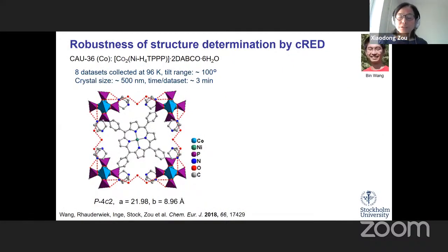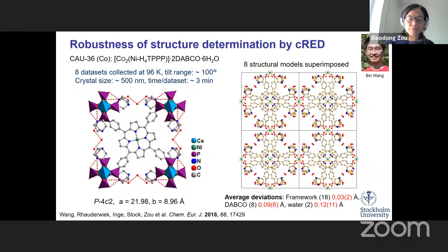And look at this structure determination today by 3D electron diffraction. And actually, they are very robust, even though it's a new technique. And we have checked, for example, in this case, you determine the structure from 8 different data sets collected from 8 different crystals. And each of them gives the same results, as you can see here. These are the 8 structure models overlapped. We can not only see the framework atoms, we can also see very clearly the solvents. So this is the solvent molecule, dark here. And also these are the water molecules that form hydrogen bonds. So we can really see very good details, and the structure is quite accurate.